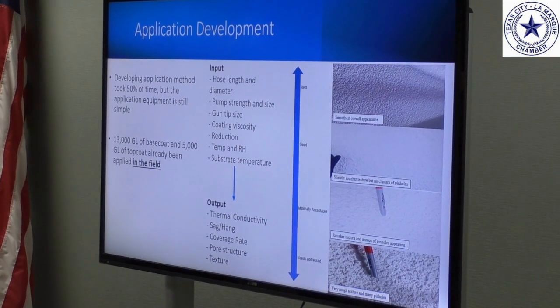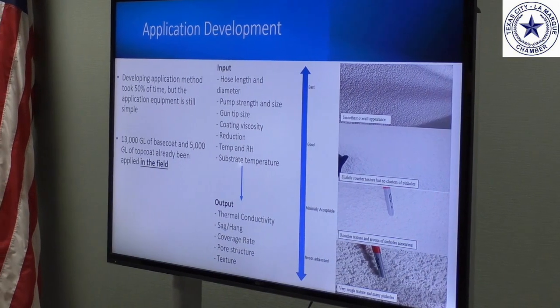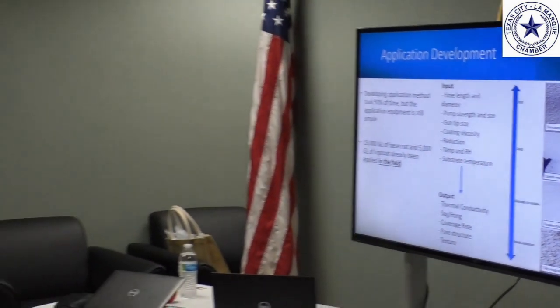So in the center, you'll see the equipment that we use. There are things that are important for us to get the right application. There's a hose length, there's a pump strength, the tip size, temperature, humidity, substrate temperature, and these are what help us to get good thermal conductivity, good sag or hang, good coverage rate, good pore structure. As I showed earlier, we have some pores in the coating that help us to get a low thermal conductivity.